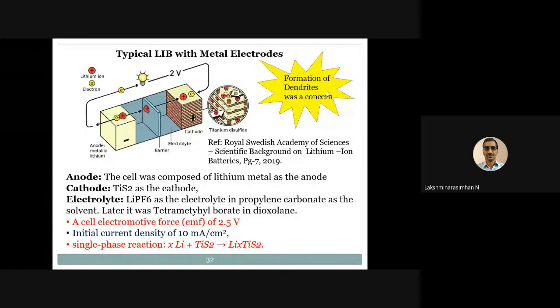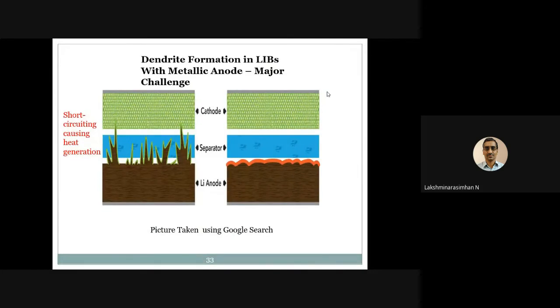That's how it went on, and the best electrolytes were taken. Lithium PF6 was used as the electrolyte, and propylene carbonate was taken as the solvent, and later tetramethyl borate and dioxolane. All these electrochemical things were happening, and electrochemical engineers came up with bright solutions which gave a cell electromotive force of 2.5 volts. The initial current density was 10 milliamps per centimeter square. All those things were happening, and there was some issue.